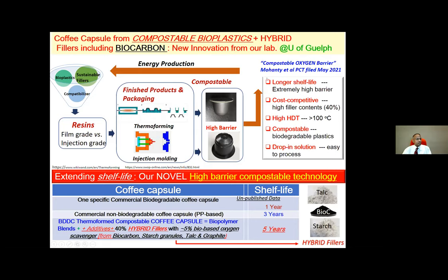So this is a compostable oxygen barrier that was developed, innovated here at the University of Guelph. This provides an extremely strong shelf life because any coffee is very oxygen sensitive. So if oxygen enters into this package and interacts with the coffee, that destroys the taste of the coffee. So it needs to be oxygen barrier sensitive. It is cost competitive, as we could incorporate around 40% of inexpensive filler into the biodegradable plastic. And it is a very high barrier. And you do not need extra processing or manufacturing in the industry. It's a drop-in solution. And they are compostable because we are developing this from the compostable plastic.